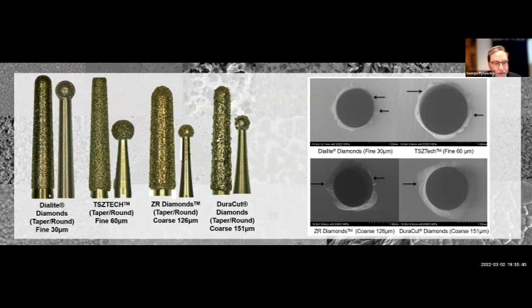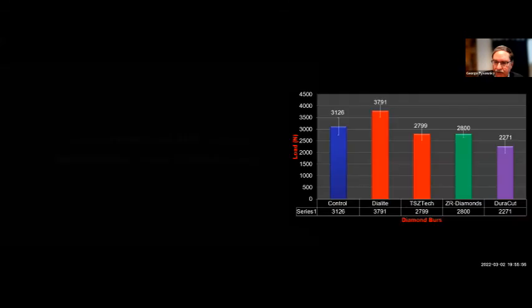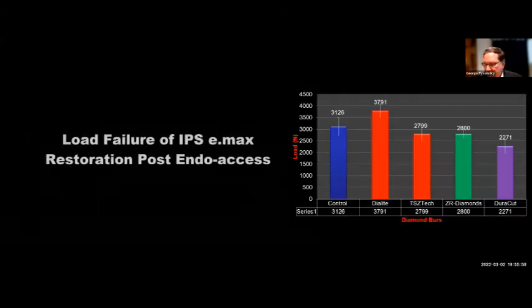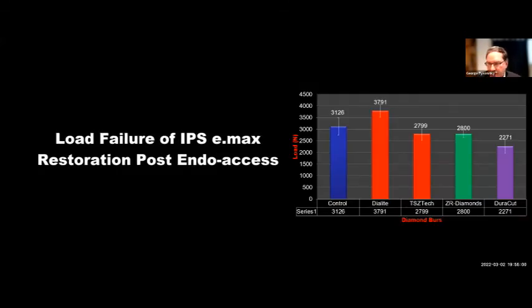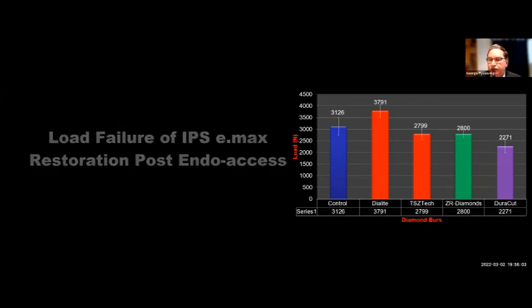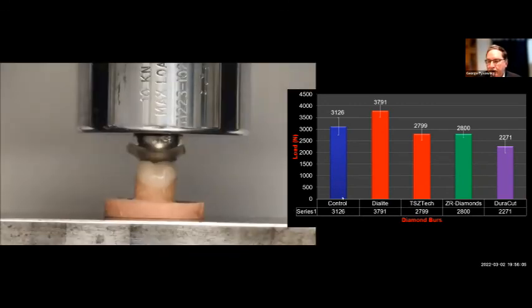So here we have a 30 micron, a 60 micron, 126 micron, and a coarse diamond. And on the right side, you can see some of the peripheral damage that occurred from these types of restorations. And then in a loading study where we loaded these materials to fracture, you can see an unpolished crown at 3000. When we did an access opening with a fine diamond of 30 microns and bonded a filling in there, it actually went up in strength.